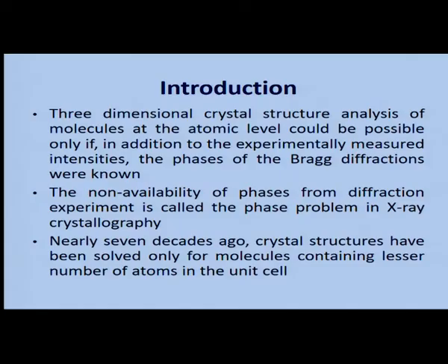As we have seen from the previous episodes, three-dimensional crystallography analysis means that for every atom constituting the molecule, we get three positions of the atom, that is, three dimensions, for which the molecule has to be crystallized first. When we say crystals in single crystal X-ray diffraction, we mean sizes of about 0.2 millimeter. The length should be 0.2 millimeter, breadth 0.2 millimeter, and thickness 0.2 millimeter.